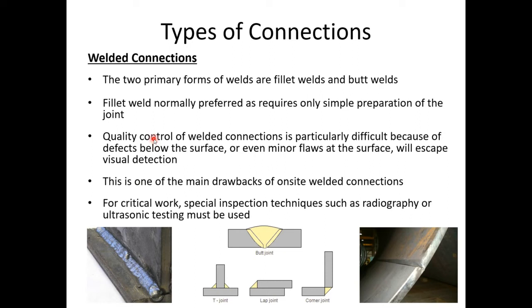The quality control of welded connections is particularly difficult because of the defects below the surface that you can't see, and even minor flaws at the surface will escape visual detection. Because you can't see it with the naked eye, we have to use special techniques, like radiography or ultrasonic testing. That's called non-destructive testing. In other words, we want to know if the weld is of good enough quality without destroying the sample, without destroying the steel, without having to pull it apart. You can do an ultrasonic test, or radiography, which will show if there are any micro cracks inside it, or any defects, or any foreign material, dirt or other material that has got into the weld during the welding process.